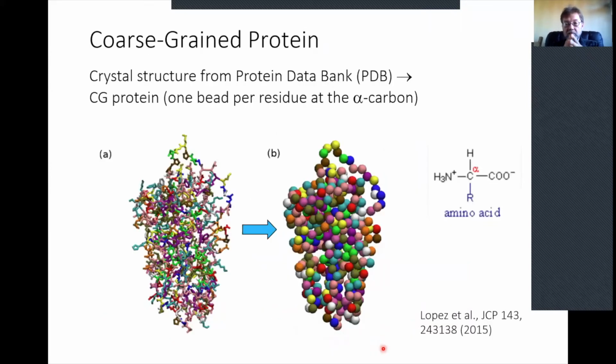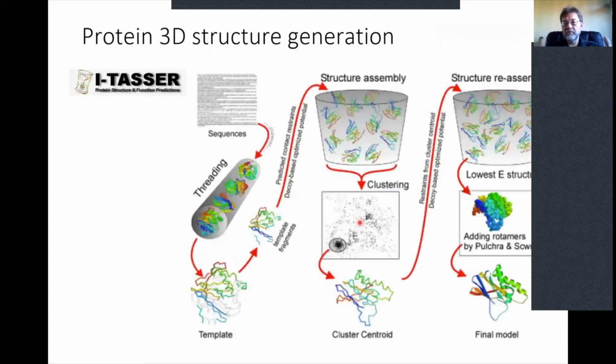Then after that, after we correct it, we can calculate the interaction of individual amino acids with particles of different size. Now we have to coarse-grain the proteins. Our coarse-grain model is as follows. It preserves the shape of the protein and the location of charges and dipoles. We put a single bead for each amino acid at the position of the alpha carbon. Then we parameterize the interaction of each bead with the potential of mean force that we calculated using atomistic simulations, and construct the overall energy of interaction of the protein using those potentials.